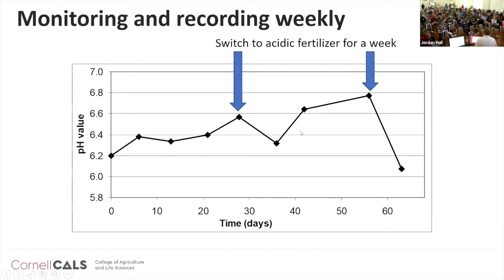So this in-house monitoring for pH and EC really is most effective if you can do it weekly or at least every 2 weeks, and then graph and track that over time. So here's an example I had of plants growing in containers with a peat perlite potting mix. We would sample them every 7 days or so. We started taking action when we got above a pH of 6.5, so we switched to a more acidic fertilizer for a week. We did that at day 28 and it was effective. We started getting out of range again about 20 days later, and we switched to an acidic fertilizer again for another week.